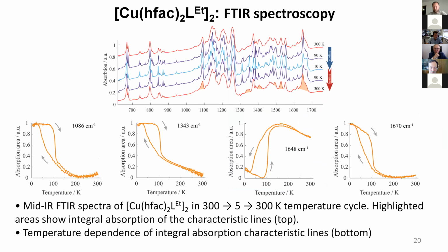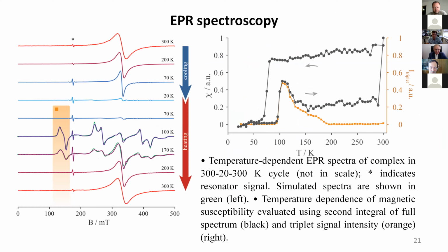We made some experiments of IR and EPR spectroscopy, and we can say that upon heating there could be a formation of an intermediate phase with an asymmetric structure, in which in the binuclear copper fragment only 1 copper-nitroxide pair is coupled. So this provokes structural crashes and magnetic behavior.